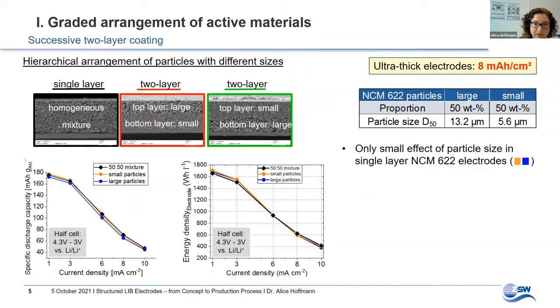Here I show experimental results that we gain from ultra-thick NCM622 cathodes produced by successive two-layer coating. The suspensions differed in NCM particle size. All electrodes in this study were produced with the same areal capacity as high as 8 milliampere hours per square centimeter and the same overall density.